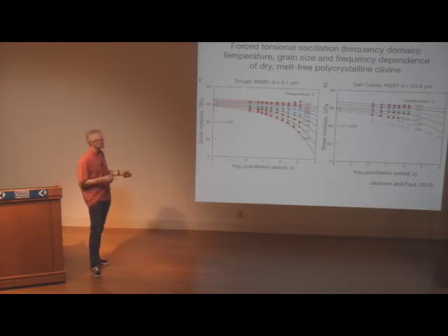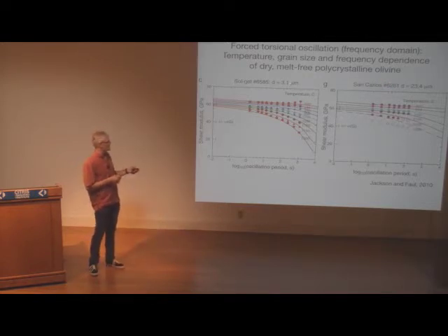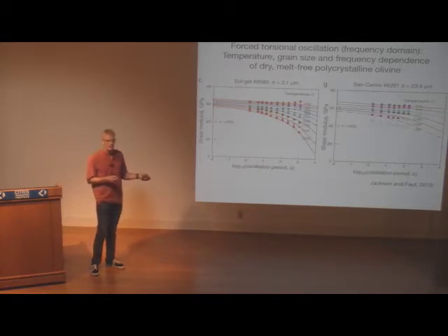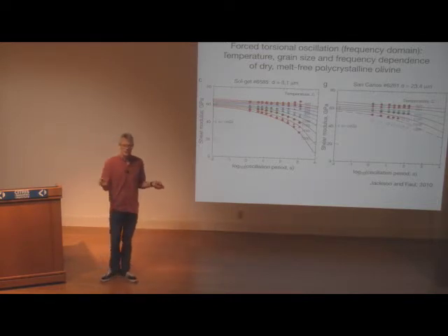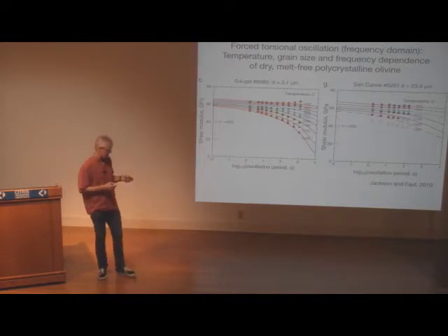And this just illustrates that you have a grain size dependence. Very fine-grained, the modulus is much lower. More coarse-grained, you have a higher modulus. These are experimental grain sizes of the order of microns. You then have to extrapolate that to millimeter to centimeter grain sizes in the mantle.